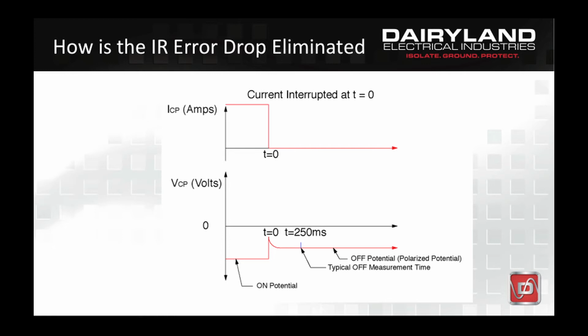The difference between the on potential and the off potential is the IR voltage drop error component that was eliminated. This illustrates the difference in potential when measured with respect to a reference electrode with the rectifier current on, which includes the IR drop error component, and with the rectifier current off, which excludes this error component and represents the polarized potential of the structure. Had this error term not been eliminated, the pipeline would appear more electronegative and better protected than it really is. All off waveforms will not look like the ideal example shown in this slide.